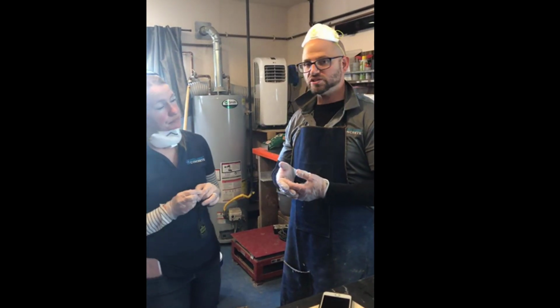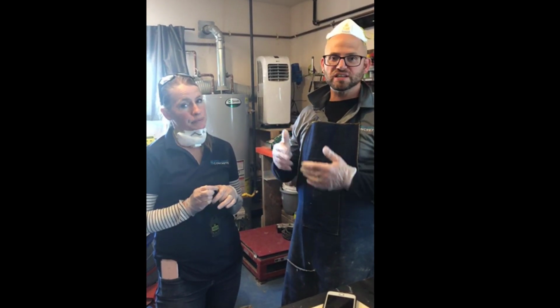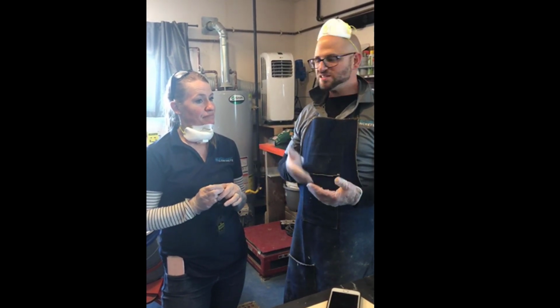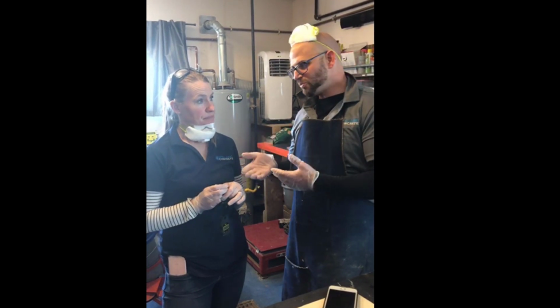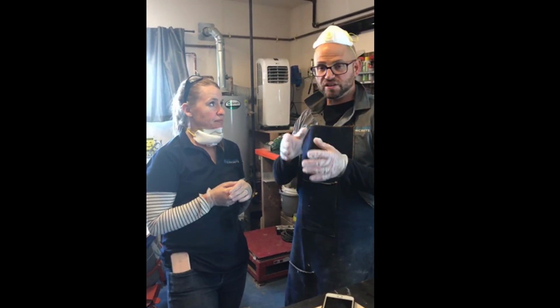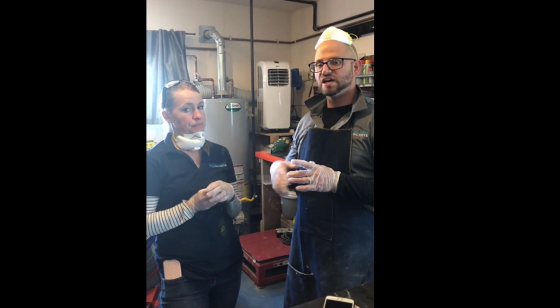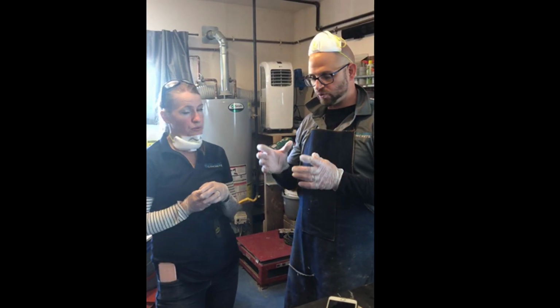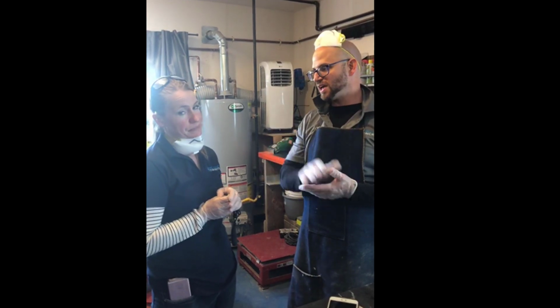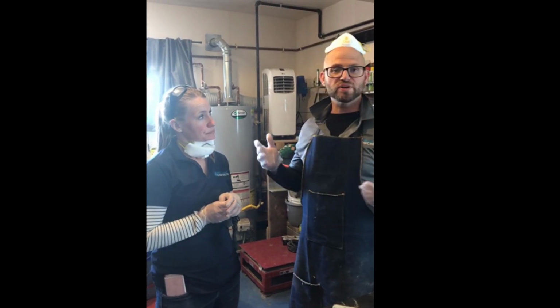So to answer El Khalil's question, we're trying to create cracks. We're trying to simulate what you're going to see in the operational world and then test it from there. If we were going to make a clean cut, we can actually have some contamination from the saw that we're using. But more importantly, it's not a realistic crack. The cracks that we're trying to simulate are either the fatigue cracks from loading to 40% of what the failure load was, and then the all-the-way-full crack, where the failure was. Then we glue it back together, creating that window all the way through the concrete, where we're just creating that capillary absorption from the crack or the fatigue crack. So yeah, more realistic. That's why we didn't do that.